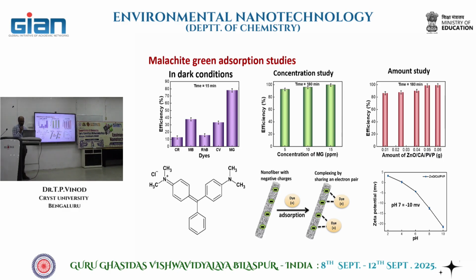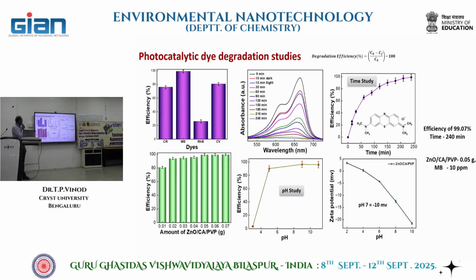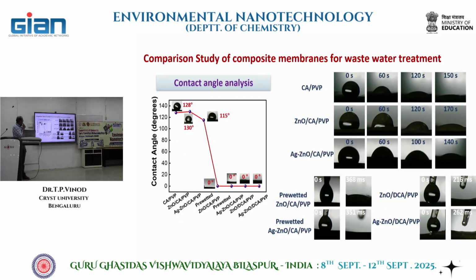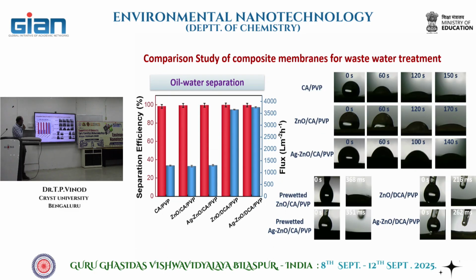Now we tested it for degradation of dyes. So we had this zinc oxide also there. Zinc oxide usually is used for dye degradation due to the photocatalytical properties. Since that zinc oxide was incorporated in this fiber also, we were able to do the dye degradation also. So I'm not going to the details of it. Then yeah, contact angle also I mentioned already.